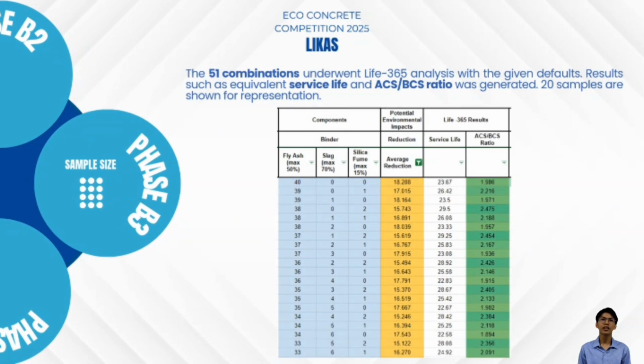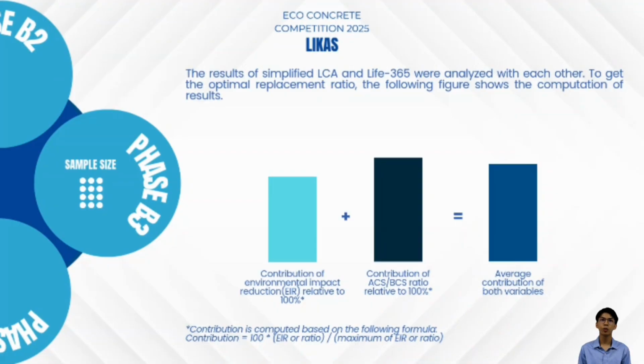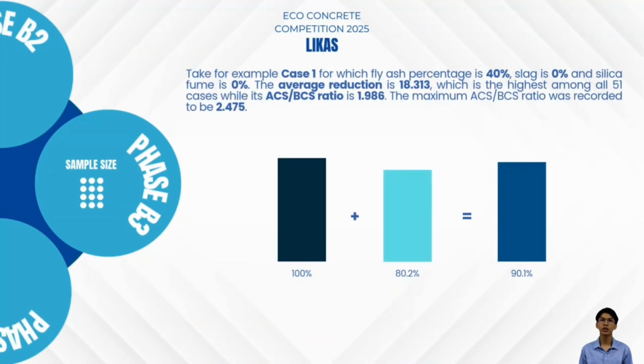For phase 3, these 51 combinations have their service life computed using Life 365. The results of both the LCA and Life 365 were analyzed with each other by computing their contribution relative to the highest value recorded. For example, using case 1 with fly ash being 40%, the contribution of EIR is recorded to be 100% since it has the highest EIR out of all the qualified samples. Meanwhile, it has a contribution of ACS-BCS ratio of 80.2%, making the final average 90.1%.